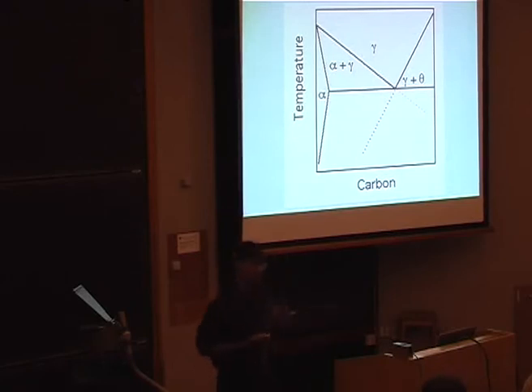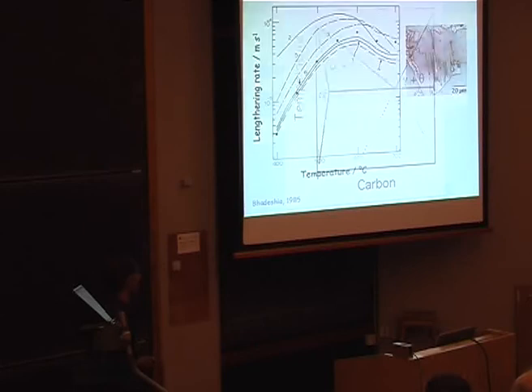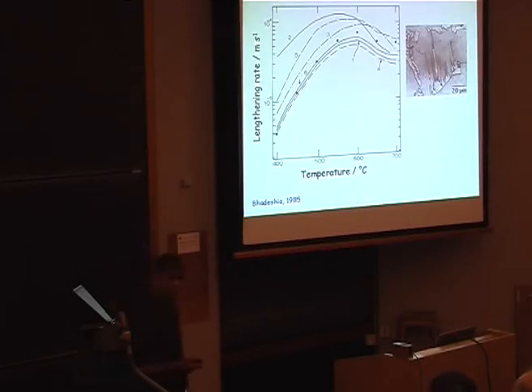Now, do I extrapolate them as straight lines because I want to do transformations at low temperatures, or should it be like that? Or what is the method that I use for extrapolating those phase boundaries? Well, depending on the method that I use, I can get an order of magnitude difference in the kinetics of transformation. But that's simply not good enough.